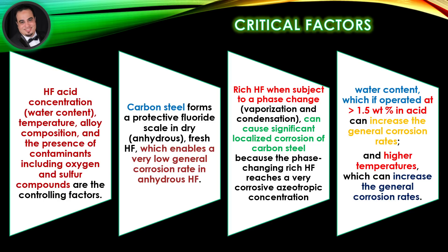Carbon steel forms a protective fluoride scale in dry, anhydrous fresh HF, which enables a very low general corrosion rate in anhydrous hydrofluoric. Rich hydrofluoric, when subject to a phase change such as vaporization and condensation, can cause significant localized corrosion of carbon steel because the phase-changing rich HF reaches a very corrosive azeotropic concentration.